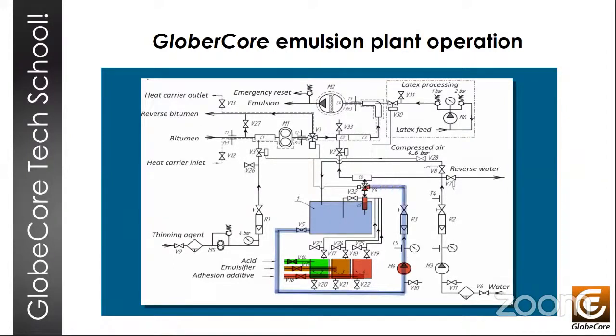The valve V4 here is in the position of blend mixing, and water circulates through the C5 injection mixer, the hydrodynamic mixer. Vacuum is created in the injection chamber of the C5 mixer and it draws in all the ingredients. By opening valves V17, 18, and 19, the operator, according to the product formula, dissolves all these ingredients in water. After 30 minutes of M4 pump operation, this blend in the tank is ready.